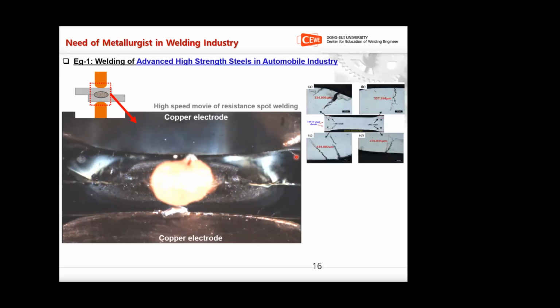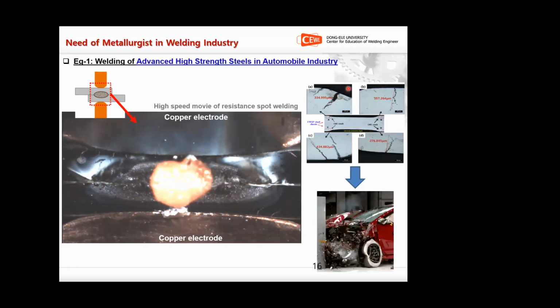And after the welding, if you take a cross section of the same weld, we can see very large cracks. These are the locations of the cracks, and these cracks are not acceptable. You know the reason. Imagine that an automobile body has cracks before a crash; then you cannot ensure passenger safety. So these cracks are not acceptable. We have to eliminate these cracks.